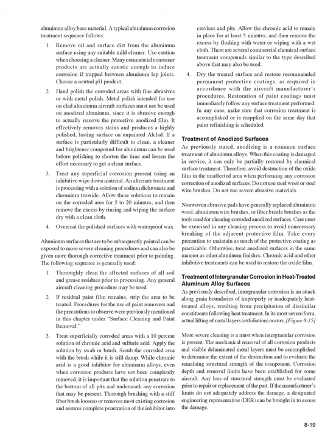3. Treat any superficial corrosion present using an inhibitive wipe-down material. An alternate treatment is processing with a solution of sodium dichromate and chromium trioxide. Allow these solutions to remain on the corroded area for 5 to 20 minutes, and then remove the excess by rinsing and wiping the surface dry with a clean cloth. 4. Overcoat the polished surfaces with waterproof wax.